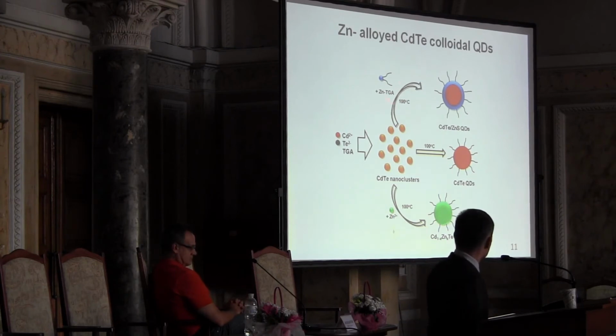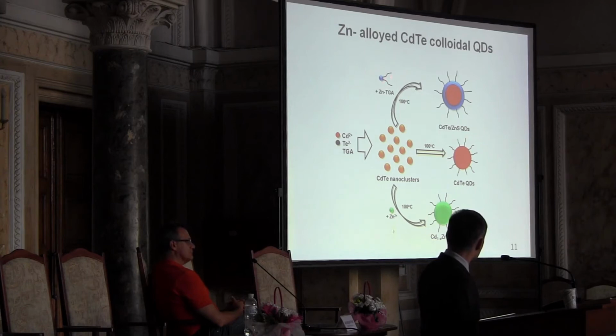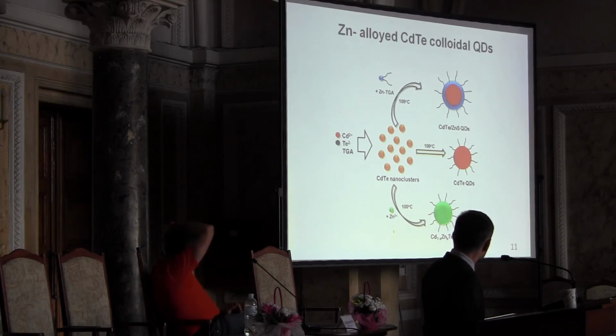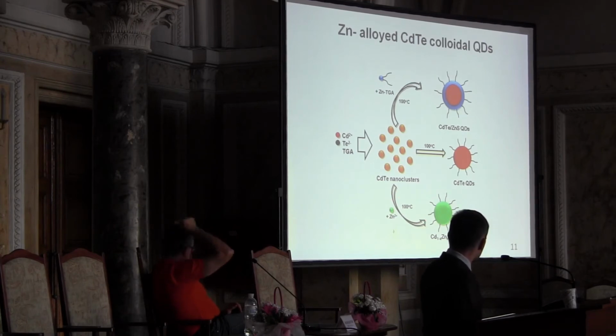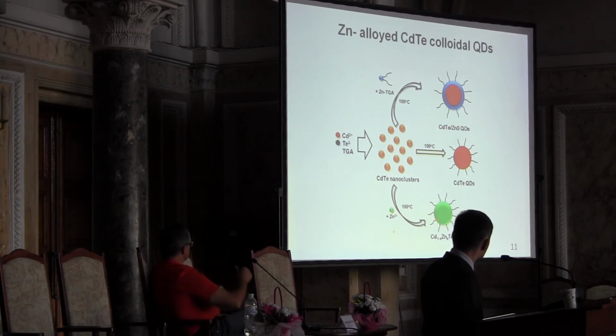For example, if you use zinc in the form of a thiol compound, add it to the clusters of cadmium telluride and heat it up, it takes time and effort for zinc to leave this complex and go into the particle. Basically, you end up with a core shell structure. And if you do not add any zinc, you have just growth. And if you add zinc ions not as a complex, but after the formation of the clusters has occurred, then it's small enough to diffuse into the particle when they grow, and you end up with basically a solid solution of zinc cadmium telluride quantum dots.